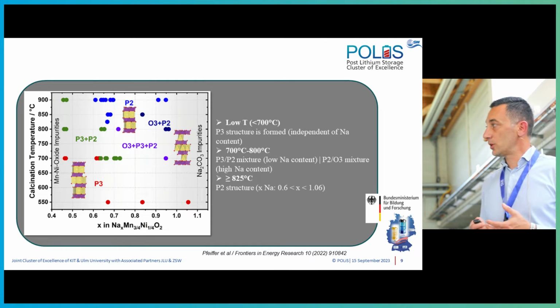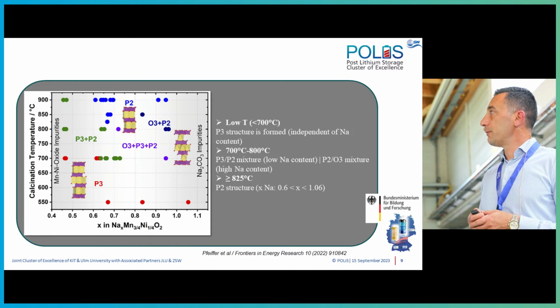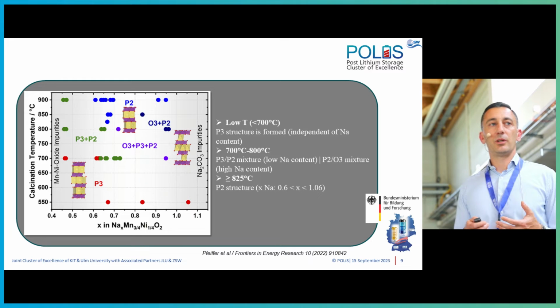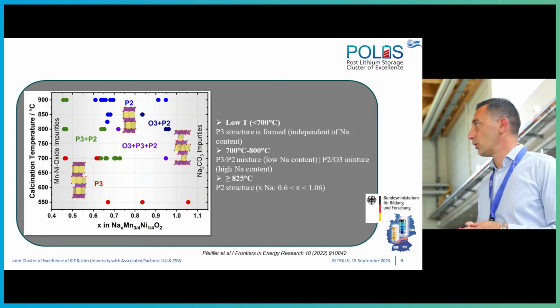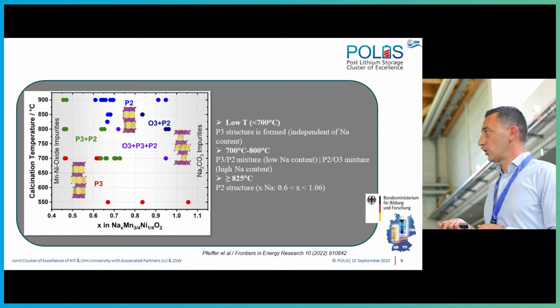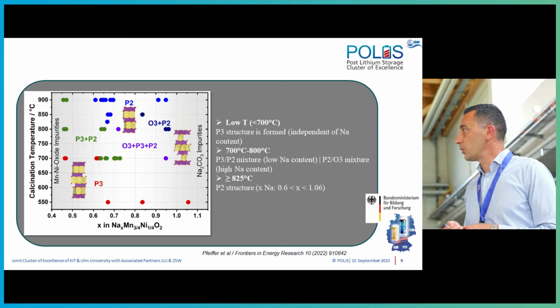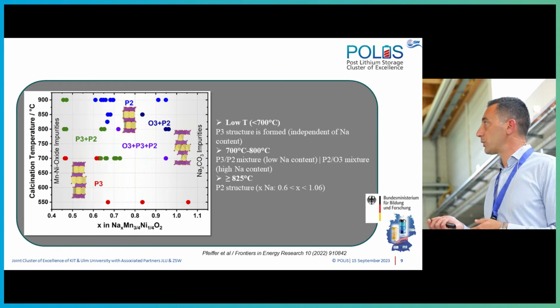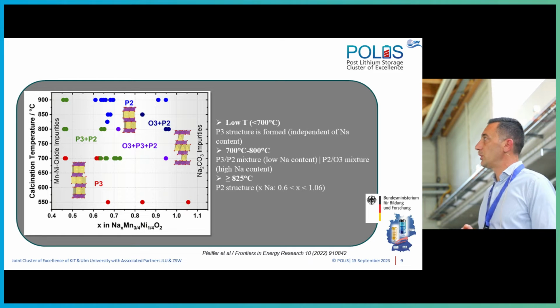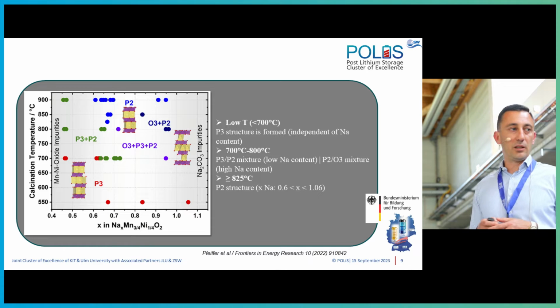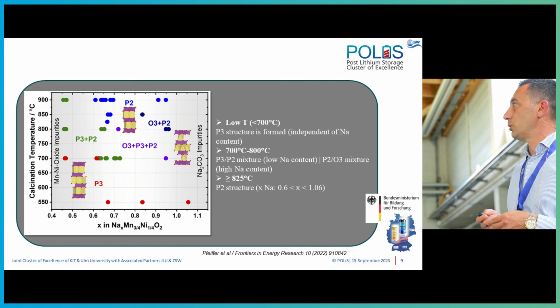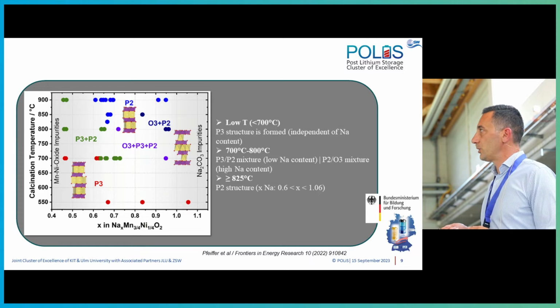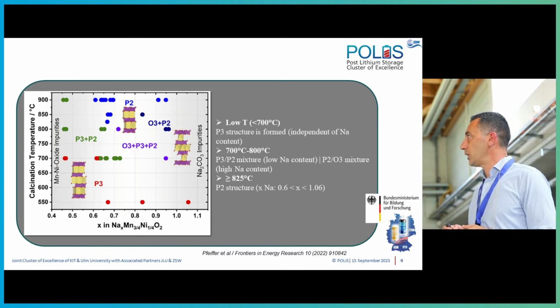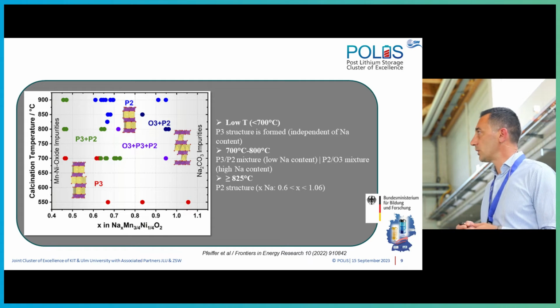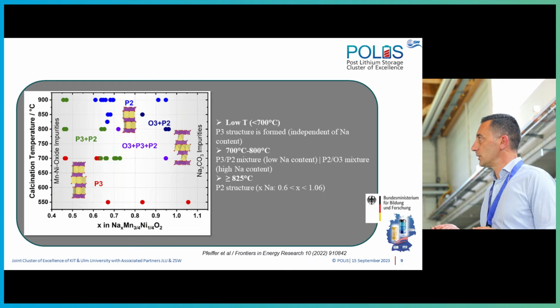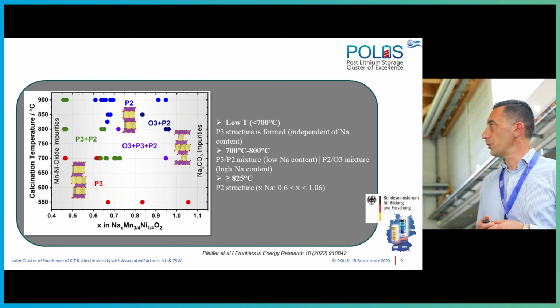What we have also looked at was how the temperature would influence the structure of the material that we have, as well as the sodium content in the structure. So what we observed was that at low temperature, so below 700 degrees, the P3 structure is formed, and this is independent from the amount of sodium that we put in the structure. When we go to 700 to 800, then we have a mixture of P3 and P2 at low sodium content. When we go into higher sodium content, then it's going to be P2 to O3.